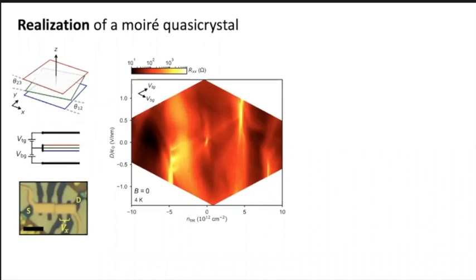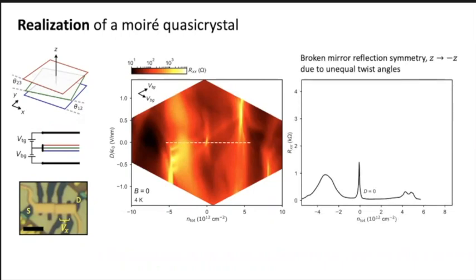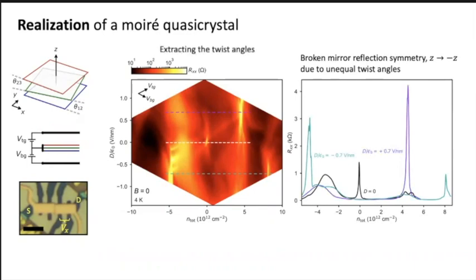And these features allow us to identify what are the twist angles involved in the structure, okay? So in particular, you take a trace to here, you have various features here, take a trace here, you have other features, take a trace through here, you have other features, okay? So how do we extract the twist angles that are involved in the structure? We can look at this feature, okay? This is a feature which happens when we polarize with displacement field and density such that, in a trace going through this, the top layer is mostly unoccupied and we're varying the density such that we occupy these two layers and we go through the band insulator state, which corresponds to a filling nu equals four.